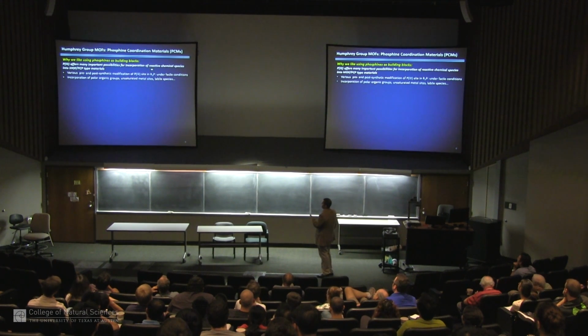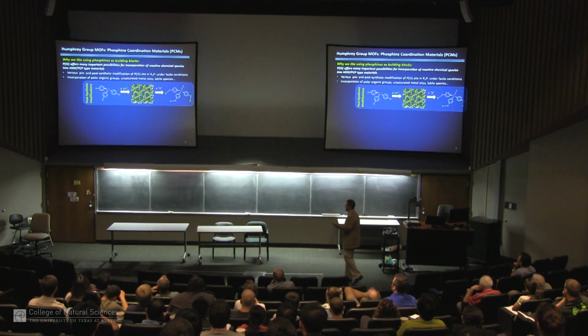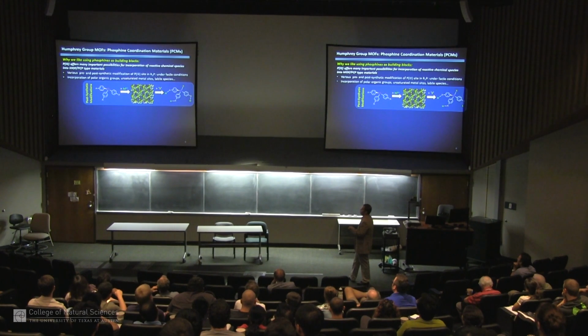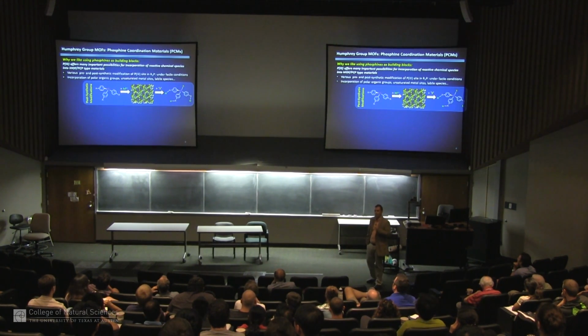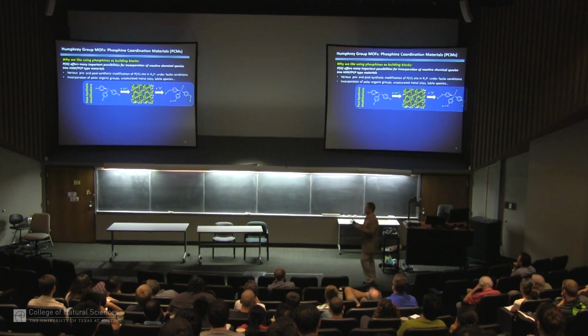We like phosphines in particular because you've got this very loose basic lone pair that allows you to do lots of chemistry inside the pore. And so here's an example of how we do this. We first have to make a phosphine ligand. And this is one of the reasons why many people in the MOF field don't easily compete with us, because they're not willing to do the synthesis of tricky ligands to begin with. They want to shake and bake. We want to make some nice ligands to start with.